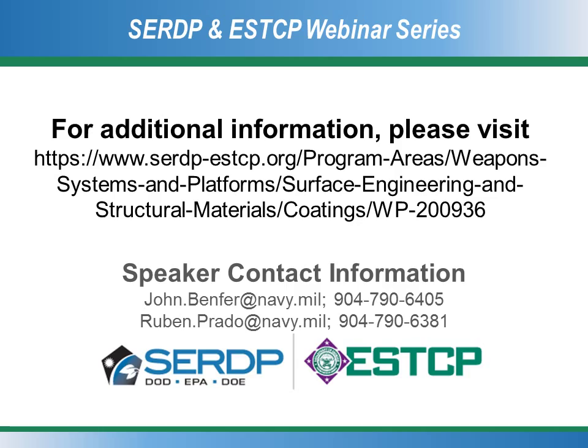Material compatibility was done two ways. One, through exposure to maintenance fluids that are common in DoD. So we do have a data set that provides information regarding the type of damage that could occur to the coating when exposed to fluids. With basic maintenance fluids that are used in DoD, we found no fluids that were detrimental to the cobalt phosphorus coating as compared to hard chrome.